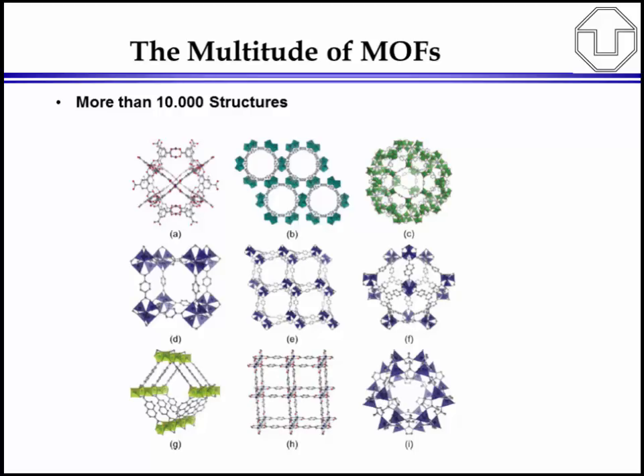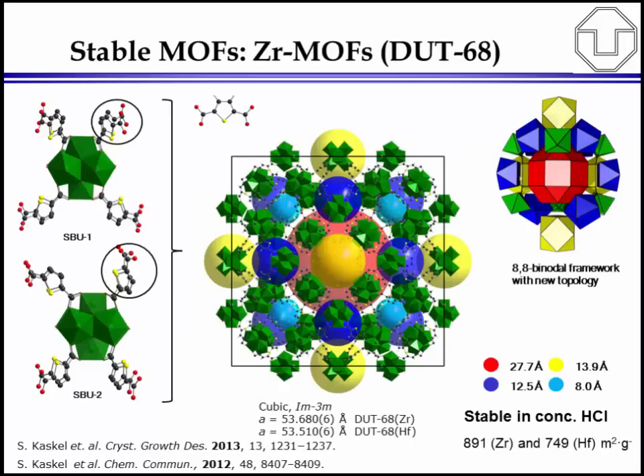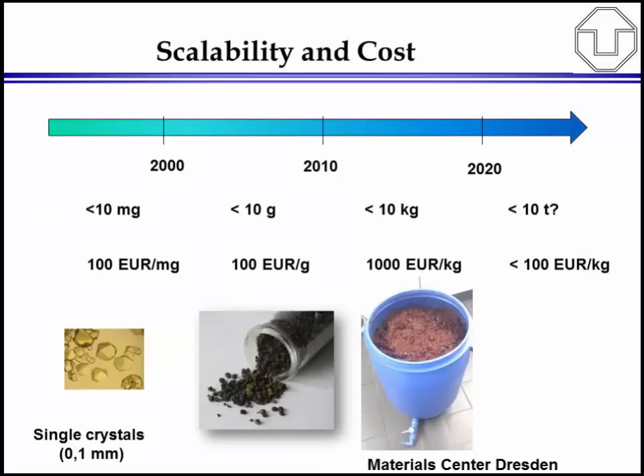Talking about stability, on the next slide you can see also that recently zirconium MOFs have been developed. Here I should also say, of course, that the most well-known metal organic framework made of zirconium is UiO-66, which is the zirconium MOF, and here we show also some metal organic frameworks that were developed in Dresden. The only thing I wanted to show is that if you choose the right synthesis and the right concept and right metal, then you can have very highly chemically stable materials, which is, for example, this zirconium MOF, which is also stable in concentrated HCl and doesn't dissolve. Okay, so this was more some introductory remarks on the structure of metal organic frameworks.